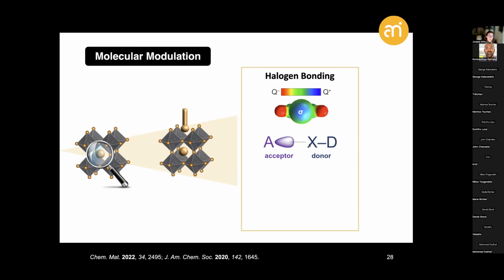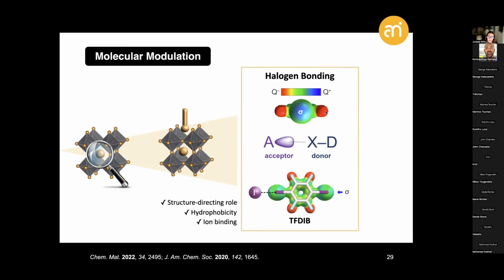which is reflected in the design of a number of, or selected representation of, these halogen bonded molecular modulators, one of which I will use today as an example to illustrate the concept, being this, for instance, tetrafluorodiiodobenzene, or TFDIB, that involves this electron withdrawing perfluorinated benzene core equipped by two iodine substituents serving as halogen bond donors, sufficiently active to form the sigma hole for the halogen bonding interactions with the surface of hybrid perovskite, such as through the halide anion halogen bond acceptors. Now, apart from this structure directing role of the perfluorinated core, it has also been relevant in the context of increasing the hydrophobicity of these materials, hopefully contributing to their extrinsic stabilization, but also ion binding capacity through both halogen bonding and other interaction with the perfluorinated core, contributed to the intrinsic stabilization.